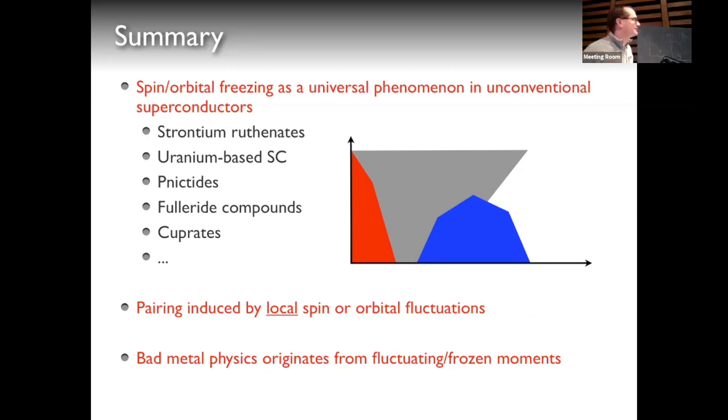All right, we can hear you. Proceed, please. Go ahead. Philip, nice talk. I just have a comment about something that is not the main topic, but I want to make it nevertheless. You discussed the optical conductivity of calcium ruthenate and strontium ruthenate in relation to the spin freezing regime. However, we have a paper with Antoine and Andy, and first author is H.T. Dang, where we do quantitative LDA plus DMFT calculations on this material, and we point out that what causes the square root of omega behavior comes from low-lying interband optical transitions. That causes the square root of omega optical conductivity. I just want to make this comment.